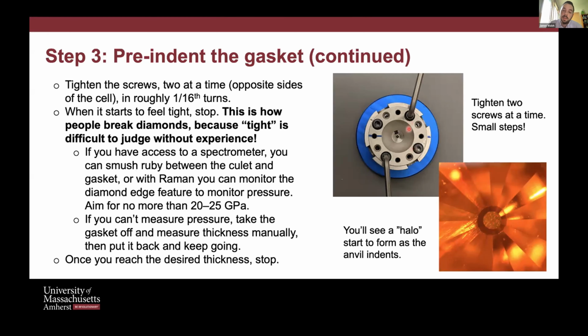That might simplify things. But start slow, very small increments, and you'll start to build up the pressure between the two anvils. I would start with 1/16 turns, and I would turn opposing screws. So you'll get more balance that way, rather than going clockwise around, because now you're kind of tightening it down in an uneven way. If you use the opposite screws, you're applying a more equal force as you go.